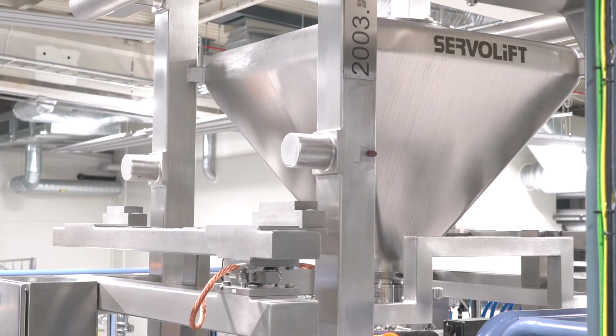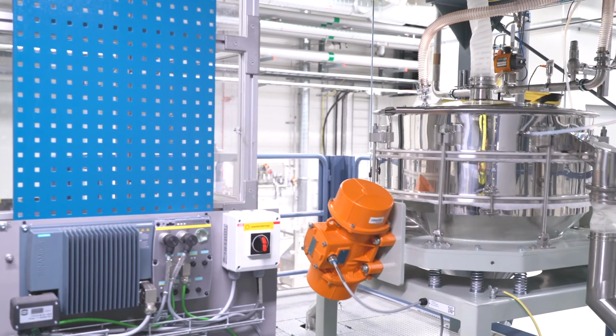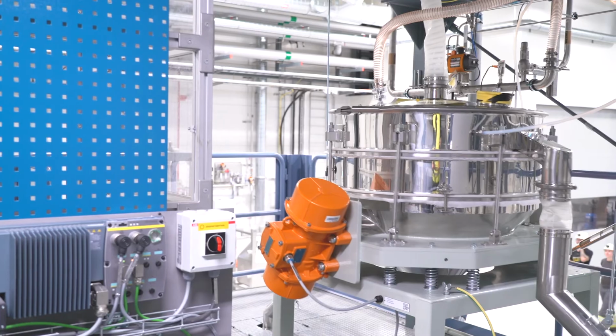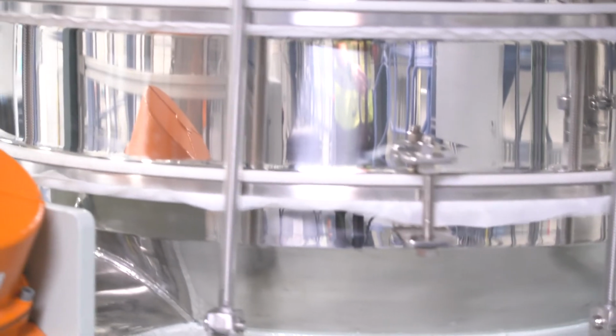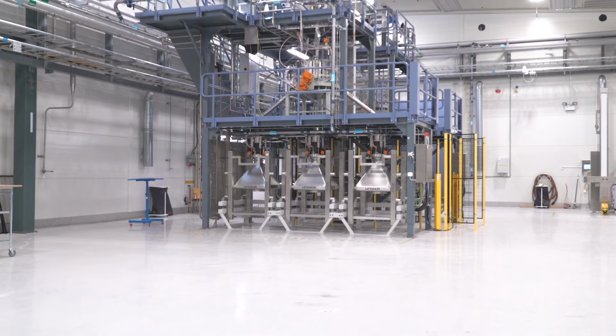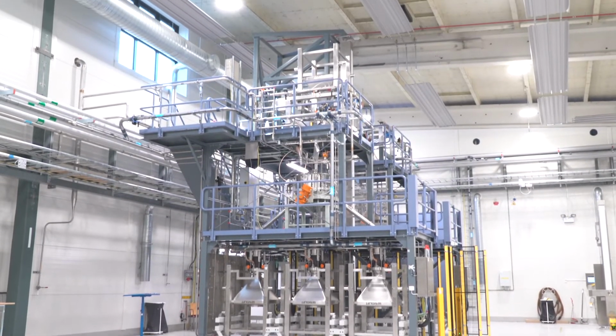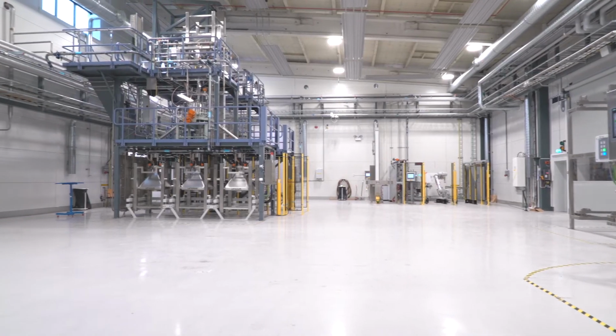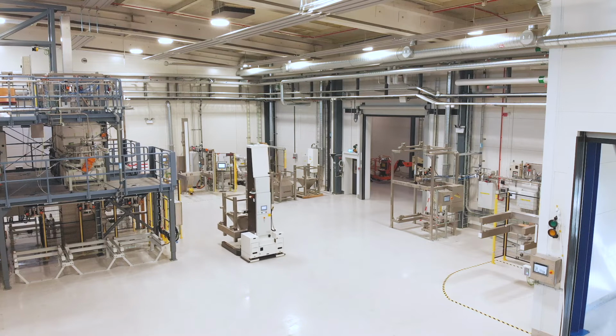The powder is released down a funnel, all the while maintaining the void of oxygen, and ends up in a double-decker sieve. We use high-frequency vibrations to separate the powder grains depending on their size, running from 0 to 500 microns, to allot the optimal fraction for each respective additive manufacturing technology. The sieving tower measures 6 meters high and features dual sieves that generate customer-tailored powder every day.